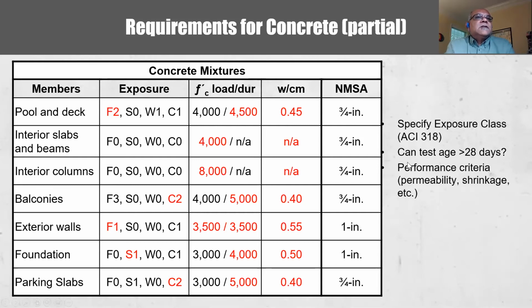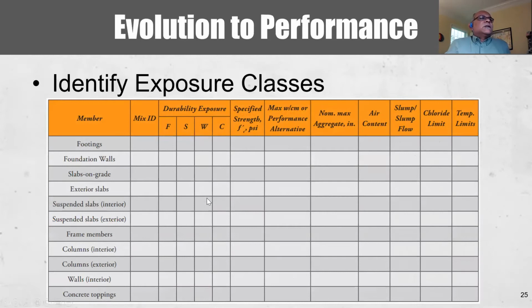Can the test age be more than 28 days? That is the traditional age for testing strength. A later age allows concrete mixtures to be a little more sustainable. And that can be for members that are, let's say, below grade foundations or footings, but do not anticipate seeing service loads for a prolonged period of time. So you establish a schedule such as this.